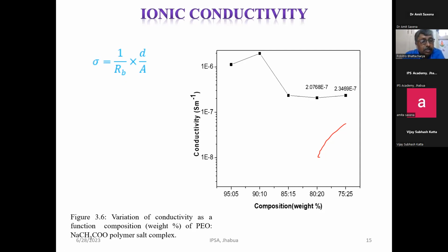Now, this is something which is very uncommon from the liquid electrolytes. In liquid, since everything is mobile, it is a fluid which is moving here and there. So therefore, though it may form higher multiplets, we don't bother about that. But in polymer, once a charge cloud is formed, it will have its own solvation cloud, and therefore it will become very difficult for that entire bigger cloud to move through. And that makes the conductivity drop down. So the conductivity drops down.